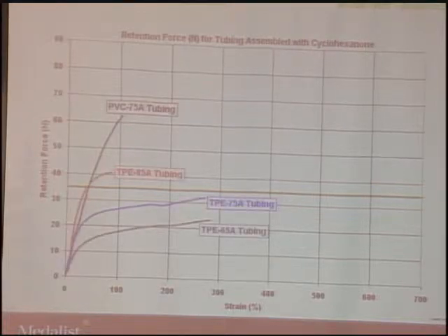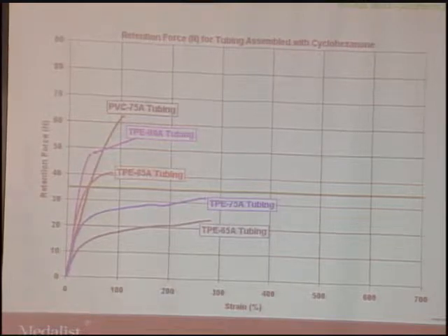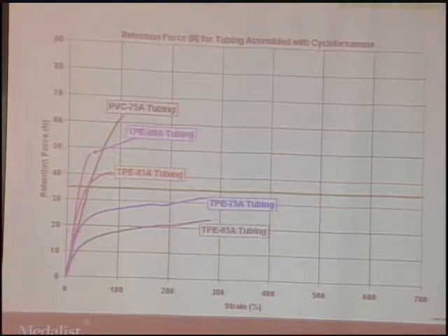However, for a TPE, if you use the same size tubing on the same connector, the retention force is not that high. And particularly as you see, if the tubing is made of a hardness below 85A, you get a very low retention force. By the way, the green line is the 8 pounds or 35.6 Newton threshold that people want. And if the hardness is 85 or above, then you can get to that force. But realistically, 98 hardness TPE is just too stiff to be used as a medical tubing. So it's very difficult.